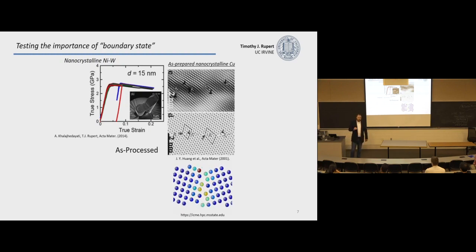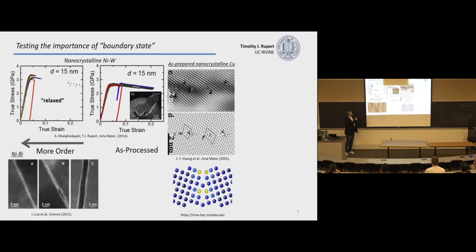All you have to do is anneal your sample at a really low temperature and let it sit there for a while. You don't want to coarsen the grains. You just want to get rid of these extra defects here. So if you go and do that, you can relax the structure and then repeat these experiments and do a microcompression type of experiment. And here you see that your material is much stronger. Now it's well over 3 gigapascals in strength, but these samples were failing much earlier. Okay, they were experiencing the shear banding much earlier.